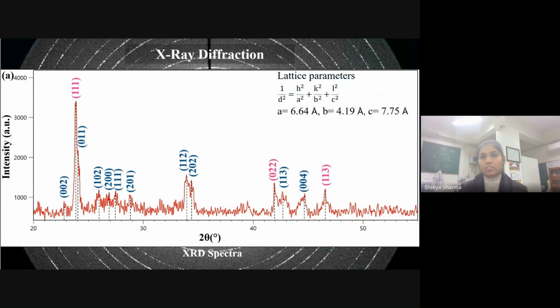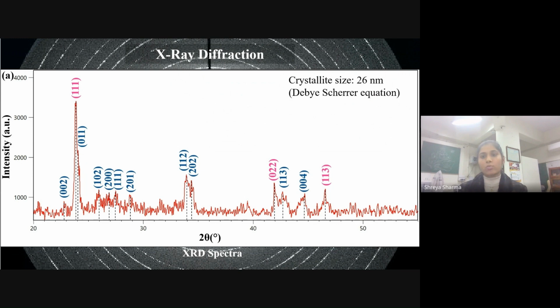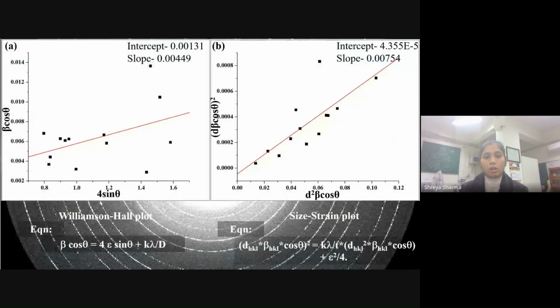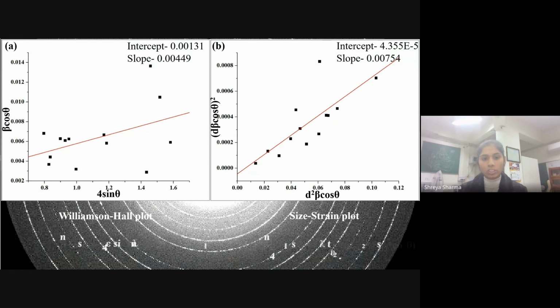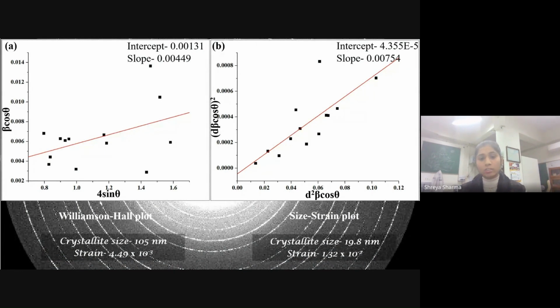The lattice parameters of the synthesized material were calculated and compared with the standard data, and they were found to be in good agreement with the standard parameters. The Debye-Scherrer equation was used to calculate the crystallite size, which was found to be approximately 26 nanometers, after which Williamson-Hall plot and size-strain plots were obtained using the equations shown here, and using the intercept and slope values of the WH and SS plots, we obtained crystallite size and strain values, which were also found to be in the nano region.